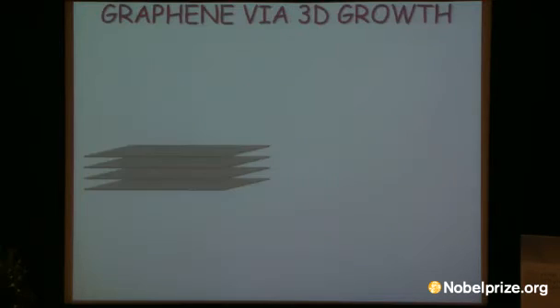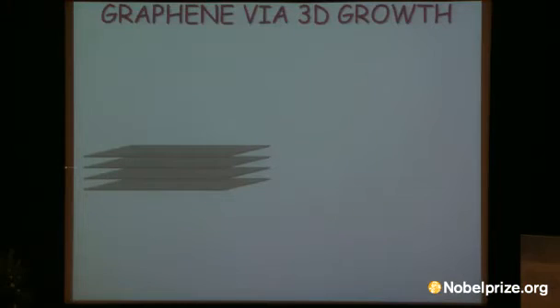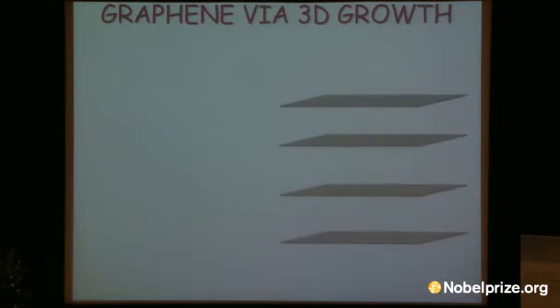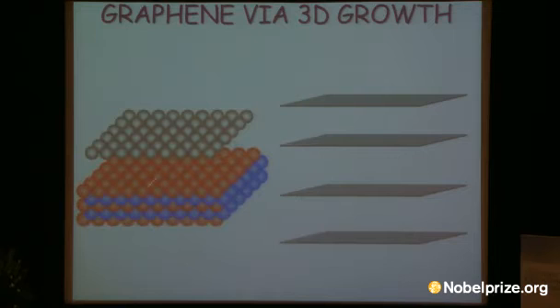How to obtain graphene? It can be obtained only through 3D growth. I do not know how to obtain it differently. So either you grow graphene as a plane of graphite and then split it, as we did, or you grow graphene epitaxially, as I described before, and then somehow remove or detach the substrate. That's the only way. This is probably why it took so long for graphene to be isolated.